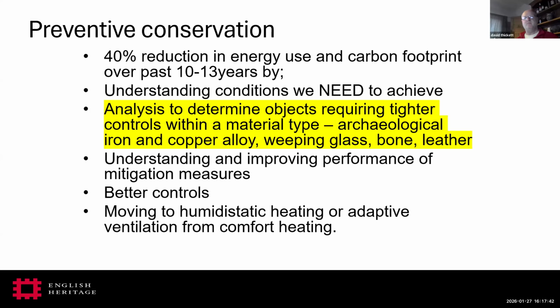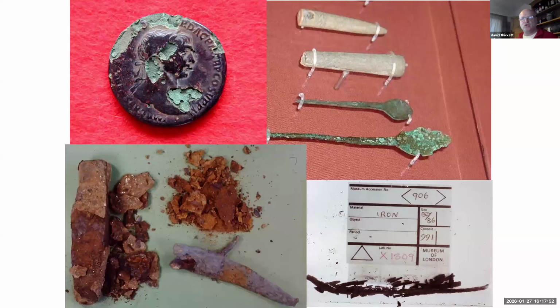But the other part has been analysing individual objects within a group that may be very similar to see which ones are stable and unstable. And just to show some examples, this is archaeological copper and iron. And as you can see, it can be extremely unstable. And if we look at the top right, the two copper spoons have very similar composition. They're from the same burial environment, quite close to each other.